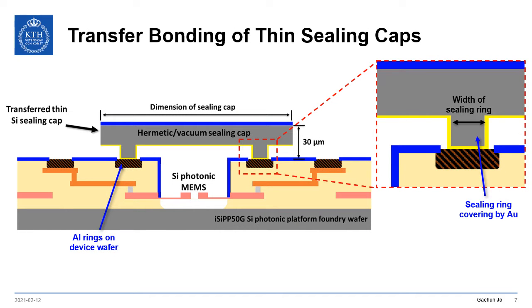Our approach is transferring 30 micrometer thin silicon sealing caps to the foundry device wafer. The thin sealing caps are patterned and fabricated in the device layer of an SOI wafer. The sealing caps consist of a flat silicon lid section with a protruding sealing ring, and it is covered by a thin gold layer.